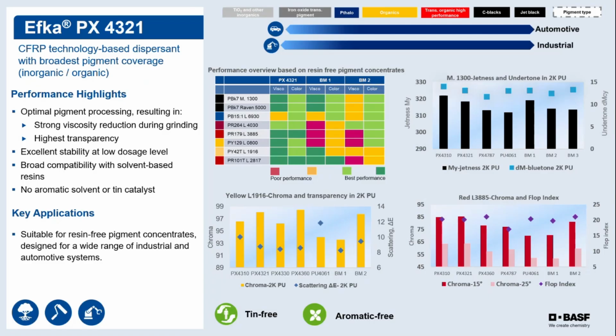So this dispersing agent will properly wet out the pigment and stabilize it, giving you very good long-term stability and then very good compatibility across a variety of different solvent resin systems. From a sustainability standpoint, there's no aromatic solvent or tin catalyst used in this particular dispersing agent product. And again, we focus on automotive at the highest level, but also this product can be used in industrial systems where color and appearance are a key factor.